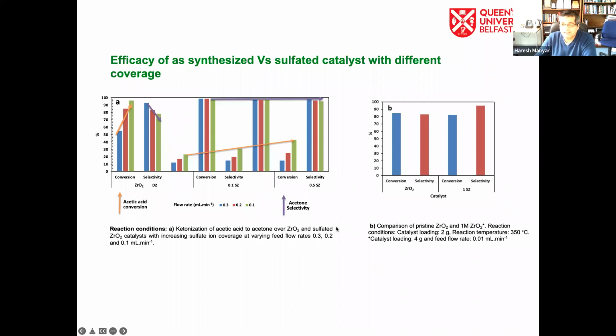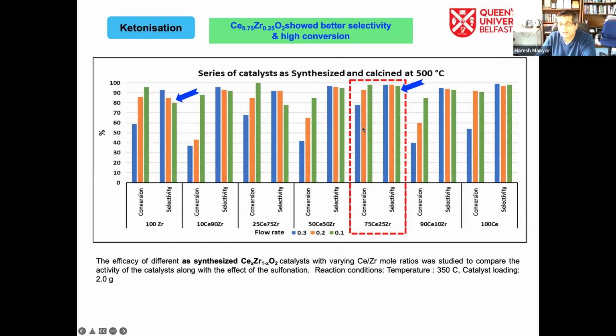So as you can see, moving from pristine to sulfated zirconium, conversion drops, but selectivity improves. We also compared it under iso-conversion levels to demonstrate that selectivity does improve for the sulfated zirconia catalytic materials. So when we move from pure zirconia to the mixed metal oxide series, then we can achieve both very high conversions and very high selectivities as well. That's why mixed metal oxides sometimes perform even better than the individual metal oxides. And you will see that a number of times during this talk today.